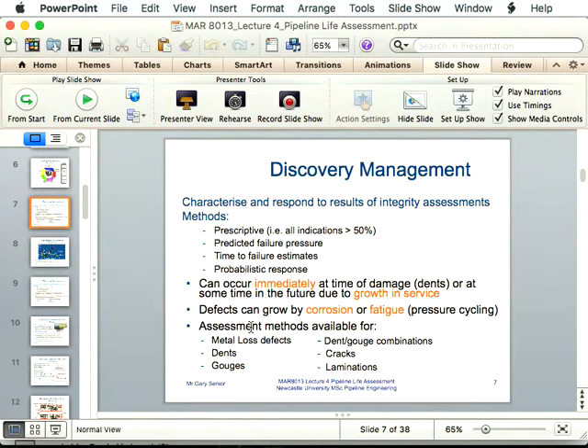Yeah, and you will sometimes get quite aggressive corrosion mechanisms, microbiological, etc., where you can lose several millimeters per year. But typical galvanic cell corrosion, which is what you normally see on pipelines, would normally be a fraction of a millimeter per year, so maybe 0.1 mil, 0.2. So if you guessed that, you guessed right, or if you knew, then congratulations. But predicting corrosion rates is really difficult. We'll come on to it after the break.